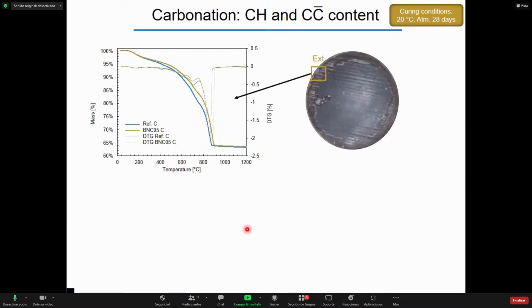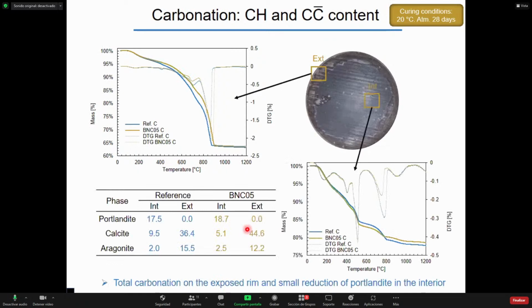In the same manner, we determined the Portlandite and calcite content of the sample at the exterior and in the interior. And we saw that at the exterior there was no Portlandite, and there was a highly carbonated material with calcite and aragonite. While in the interior, Portlandite was slightly reduced compared to the non-carbonated cement that we saw before.